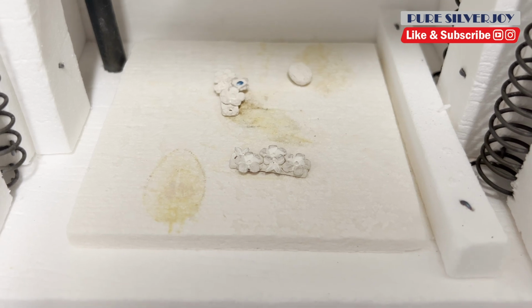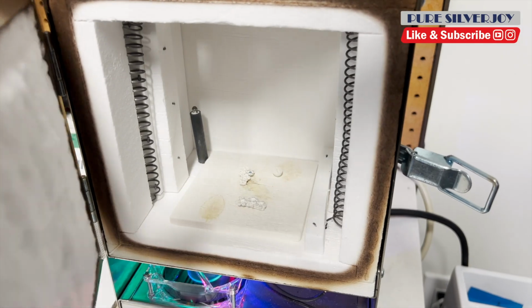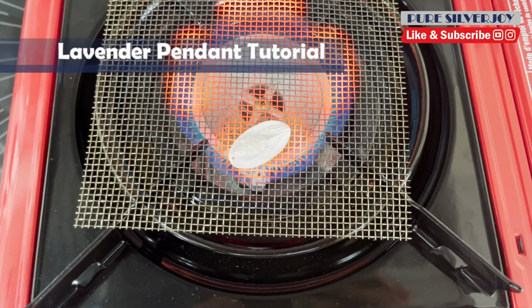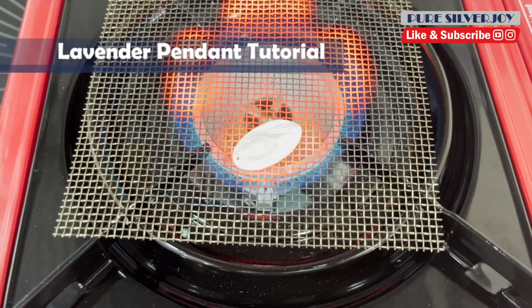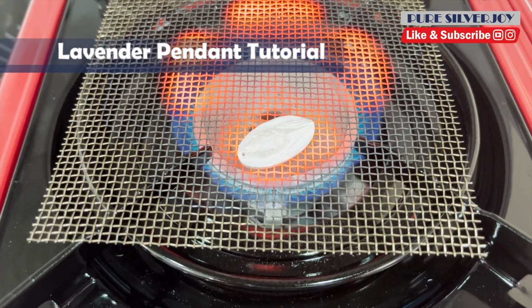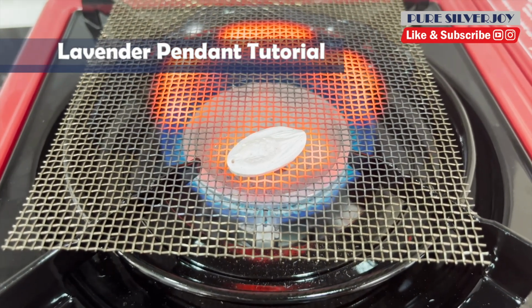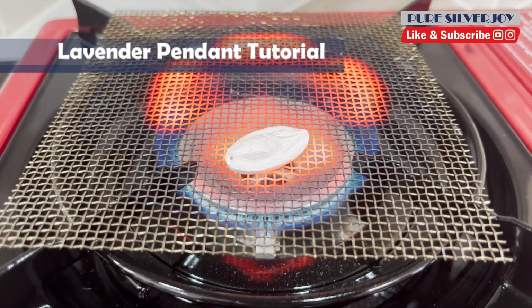Before firing, make sure your piece is completely dry. If it's still a bit damp, it could crack or bubble in the kiln. We used a kiln set to 800 degrees Celsius, or 1472 degrees Fahrenheit, and fired the piece for about 15 minutes. But if you're doing this at home, you can totally use a gas stove too. Check out our previous lavender pendant video to see how.